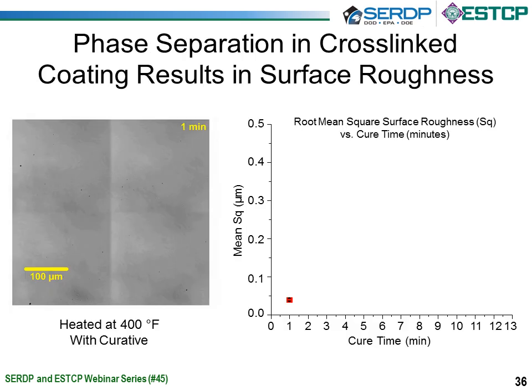Slide 36. We needed to confirm that indeed we were able to make a durable film. The image on the left is from laser confocal microscopy. If you notice the cross, the vertical and horizontal, that's simply an artifact of the stitching software where we stitched the four images together. We use laser confocal microscopy as a technique to monitor the surface roughness through root mean square, and this was a very useful technique in that it allowed us to predict the gloss or the reflectivity of the coating system.